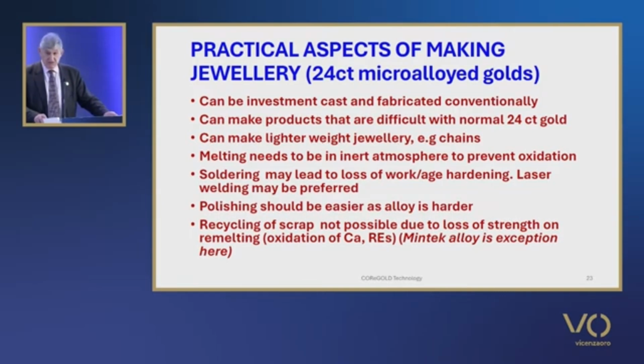Recycling of scrap is generally not viable due to loss of strength on remelting, as we've discussed earlier. The Mintek alloy containing calcium and rare earths is an exception here. However, remelting should allow the gold content to be fully recovered after use.